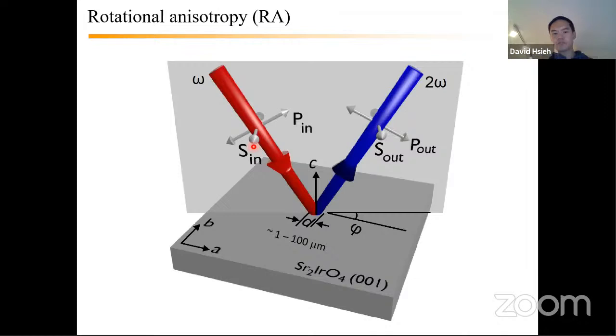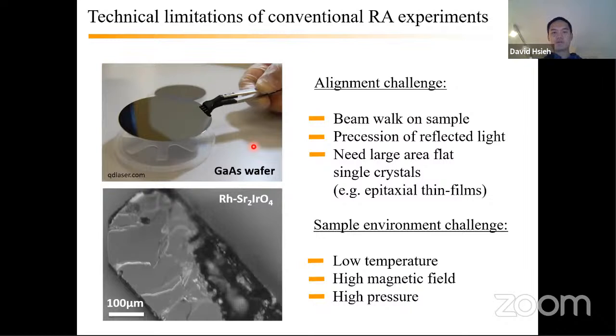So the challenge with doing this so-called RA type measurement is that there are a lot of moving parts, as you can see from the setup. Okay, so if you do it on a super flat ideal material, sometimes those non-idealities in the experiment are not as serious, but it does become dangerous when we're working with these small samples that are oftentimes non-uniform and riddled with terraces and cracks that you want to avoid, because anytime you veer from the ideal geometry, you can get artifacts in your measurement. Okay, so there are all these moving parts in the experiment.